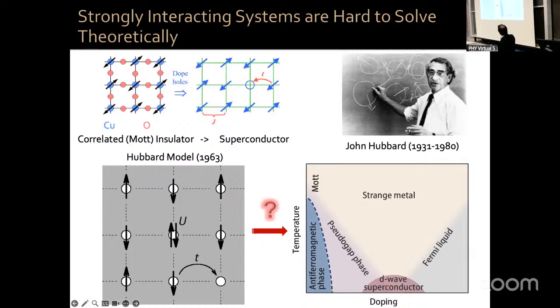So they're in this area. They would like to cool down to see this, but they have to cool down about 1 to 2 orders of magnitude, they believe, in order to reach this region. And this is something where there's no fundamental law of physics preventing this from happening, but it's technically extremely challenging. And as a result, although there has been steady progress, it's not as fast as they would like, and they have been able to observe fewer phases of quantum matter than they would have liked because they are in this high temperature regime.